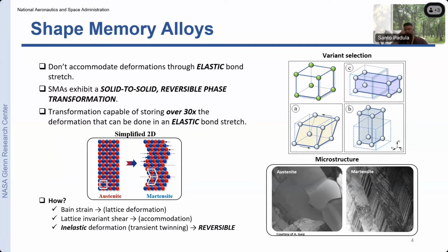In shape memory alloys, we have a very different mechanism that is activated. In these material classes, we actually, in the solid state, are doing a reversible phase transformation. It's known as transient twinning in these systems. And what we, in essence, are doing is we can start in one phase of the material. In this case, we're starting as an austenite. And then as we apply loads and stresses to the system, we actually induce a metastable phase transformation where we change the crystal structure from an ordered cubic to a monoclinic crystal. And so we actually rearrange the atoms in the solid state to a different crystal structure.